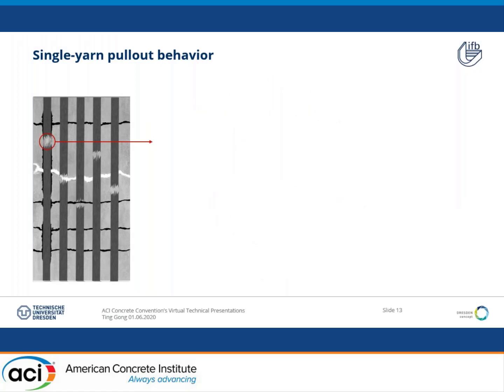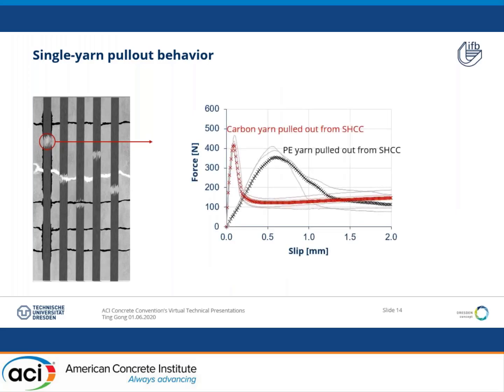Then, if we compare the pullout curves of the single carbon yarn and PE yarn, we can observe a stiffer linear branch, higher maximum pullout force, and smaller maximum slip value in the case of carbon yarn. Actually, the shape of the pullout curve is not only determined by the different shear strength or bonding efficiencies, but also by the elastic modulus of the yarn. For example, the PE yarn with lower elastic modulus will tend to be stretched more during the pullout procedure.